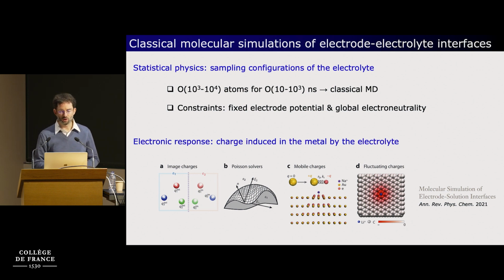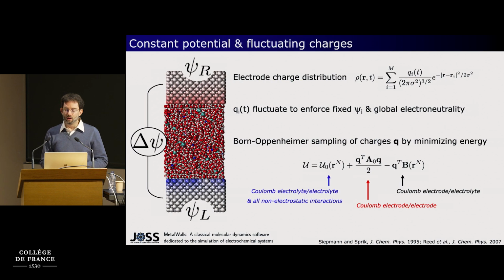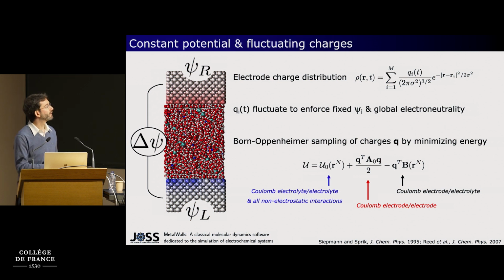And I'm going to show you some results of simulations that we do in our groups that are based on this fluctuating charge model of the electrode. So in a nutshell, the way this works is to assign to all the electrode atoms a charge which has a Gaussian distribution, because it's not completely localized on the position of the electrode atoms. It's rather diffuse inside the metal.